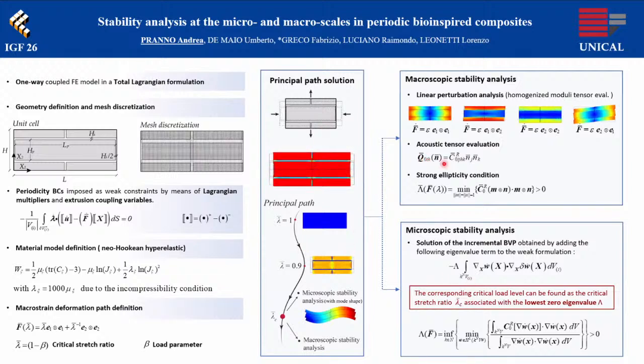The homogenized tangent moduli tensor is obtained by performing four linear perturbations, which are highlighted here in the slide. Then an eigenvalue problem is solved to evaluate the acoustic tensor. The eigenvalues are monitored to detect the first instability at the macroscopic scale. This is widely used in the literature to evaluate stability with long wavelength.